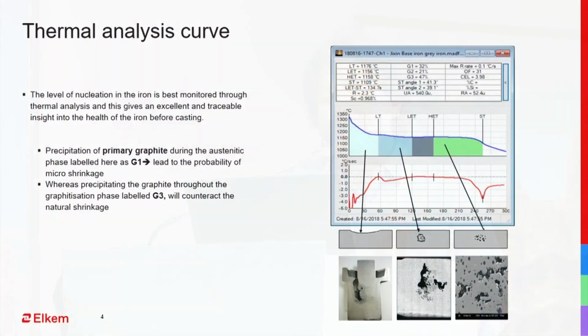By thermal analysis, before pouring castings, you will get an idea. This will give a clear idea whether there are any chances of metallurgical shrinkage. Normally in thermal analysis, this green portion, that is graphite G3, is called the graphite factor 3. If that percentage is high, normally in the case of very good castings, when shrinkage and microporosity is almost 0, in our experience we got more than 80-85% G3. That indicates your nodularity and nodule count will be high.